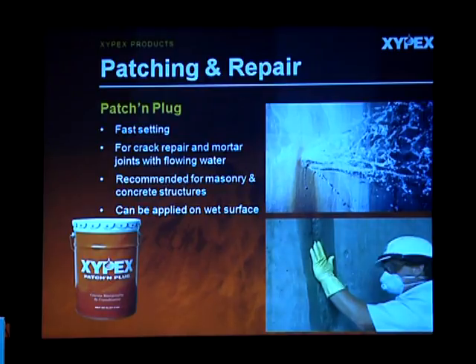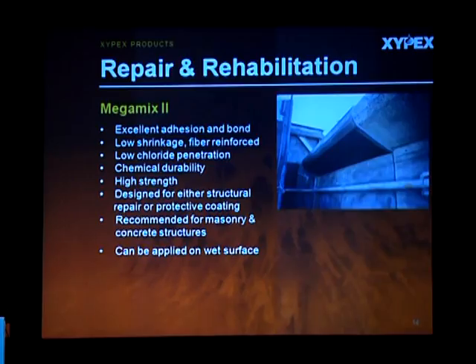It actually plugs the structure within a couple of minutes' time. The advantage with this material is that it can be applied on a wet surface. So in hydraulic structures, most of the time we have a situation where having a moisture-free surface is not practical. We would always have moisture present there. This material is very, very effective in those situations.